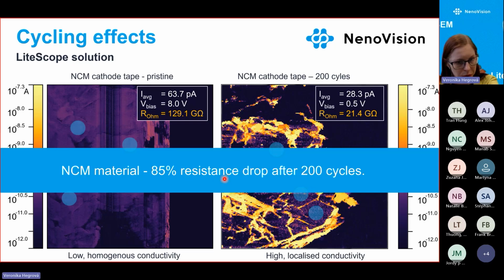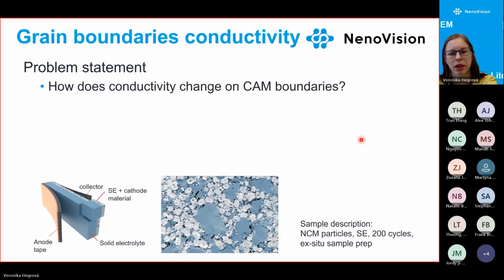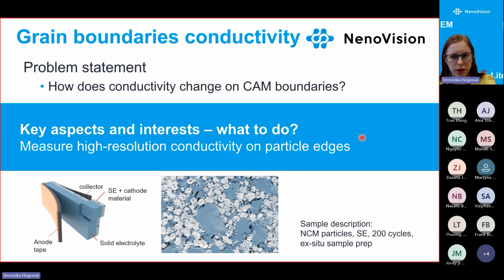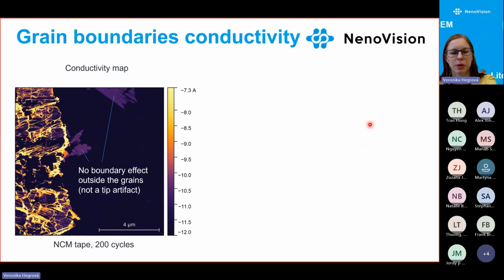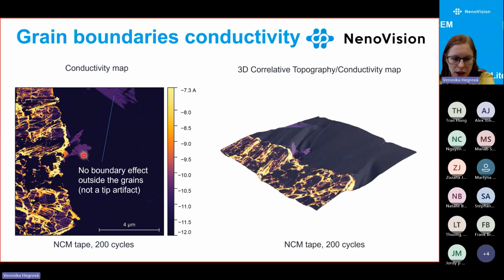And we found out that 85% resistance drop is after 200 cycles. And so we wanted to have a closer look at the edges and measure a high resolution conductivity on particle edges. So what are the edges? We had a closer look at this part, where there are many things happening regarding the conductivity. The levels are quite different.